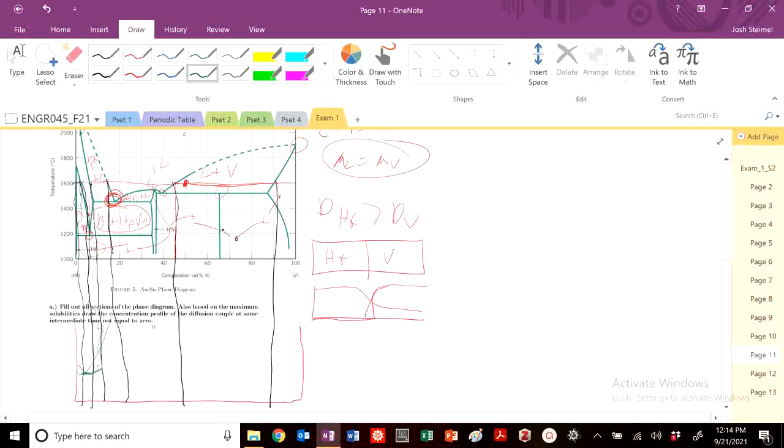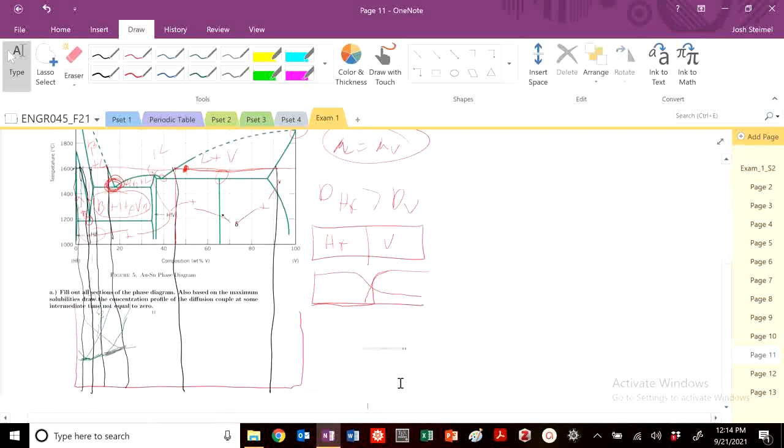And then I cross over into, again, a two-phase region with liquid. My liquid is going to be this different color, gray. Again, I'm going to have a common tangent between here and here. Any region where I'm in a two-phase region, I have a common tangent. You can see here that this is the lowest energy phase, so I'm in pure beta. Actually, we could draw this out a little bit further.